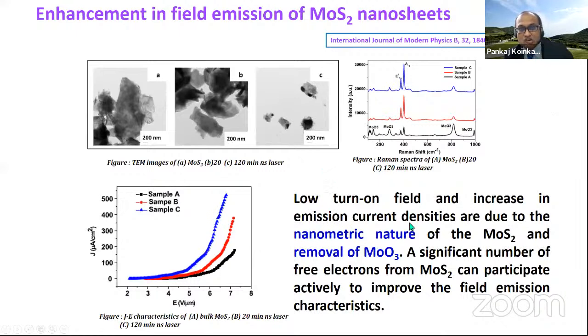Why does this increase occur? There are two different reasons. Of course, one reason is the nanometric scale. The other reason is removal of MoO3. When you look at the Raman spectra, there are MoO3 peaks, 1, 2, 3, and 4. But after laser ablation, the intensity of these peaks is reducing. It might give the sign of removal of MoO3 particles present in the bulk material. So there are two different reasons for this.